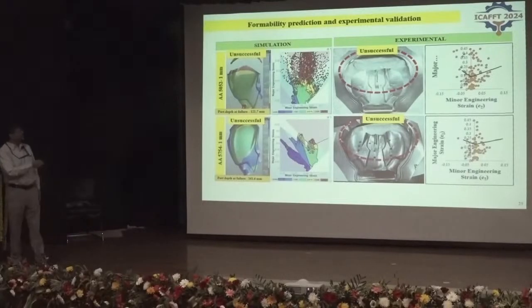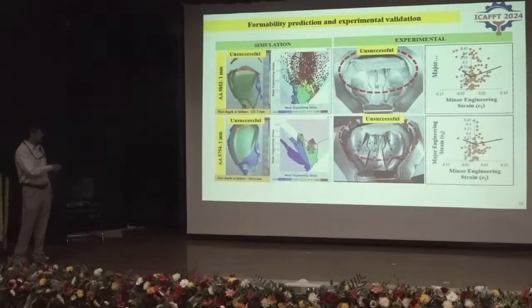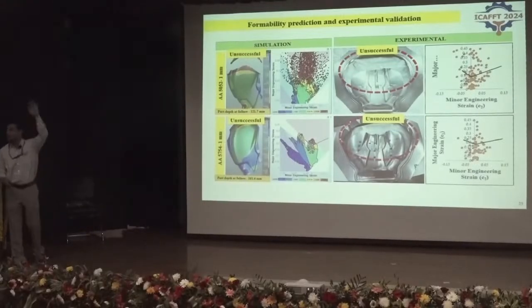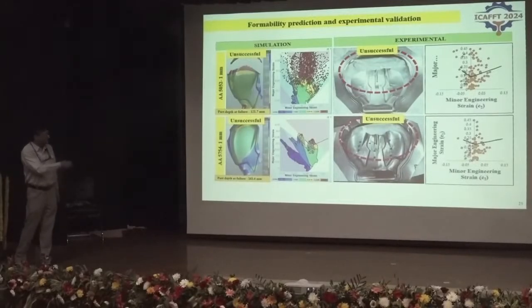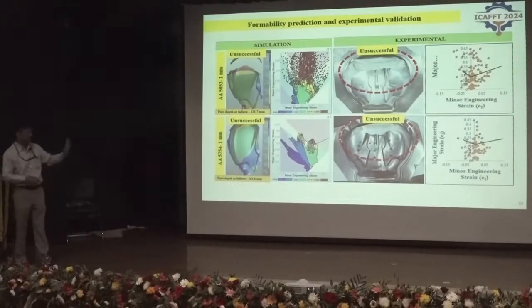And this shows the predicted results and the experimental results on aluminum alloys fuel tank manufacturing, the actual fuel tank. So we started with 1 mm. In both the cases, we were not able to form completely to the required depth. You can see 5052 failed when the part depth was 122 mm, and 5754 failed at 162 mm, whereas the required depth was like 180 mm. And experimentally also you can see that there was a complete crack, and there was excessive thinning, and the material failed in both cases.